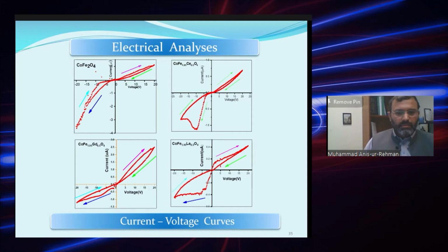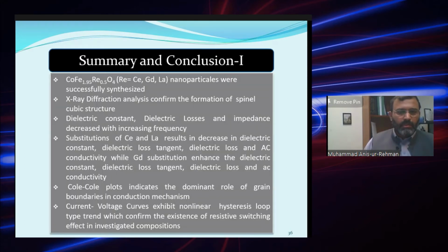Applying the current voltage curves, we can see that there is a good hysteresis when we are moving from 0 to positive voltage, then from higher to lower voltage, and then again from 0 to the negative voltages. So these hysteresis loops are very much required for resistive switching and the use of the ferrites in resistive RAMs.